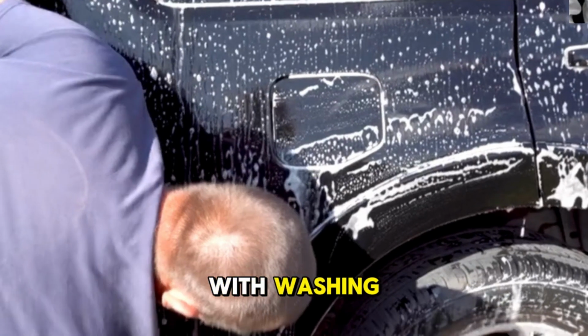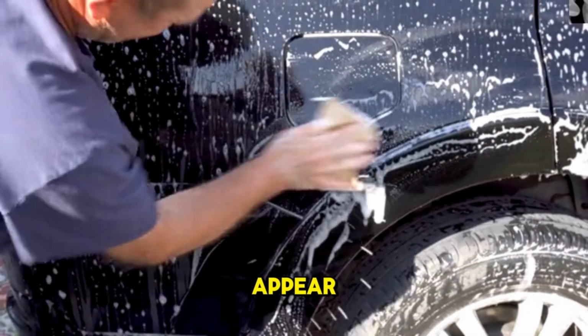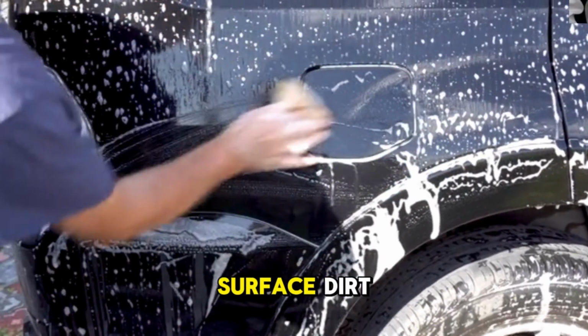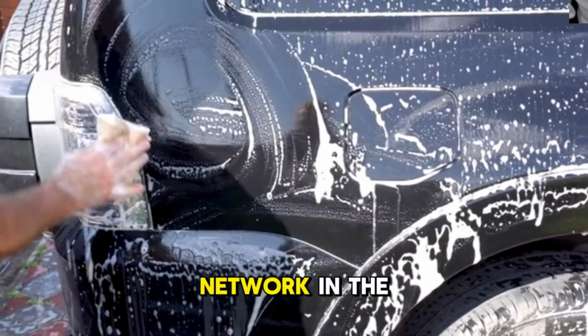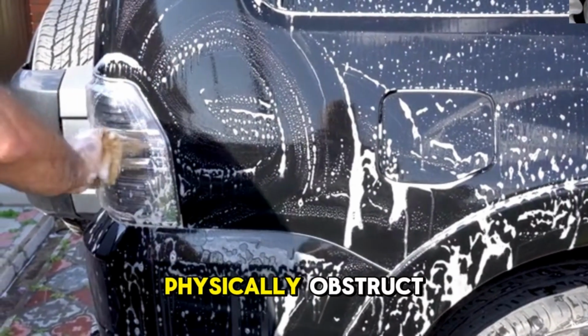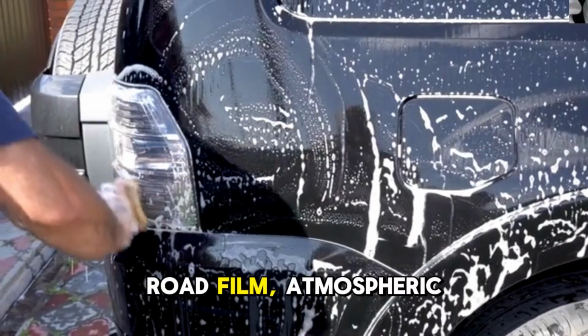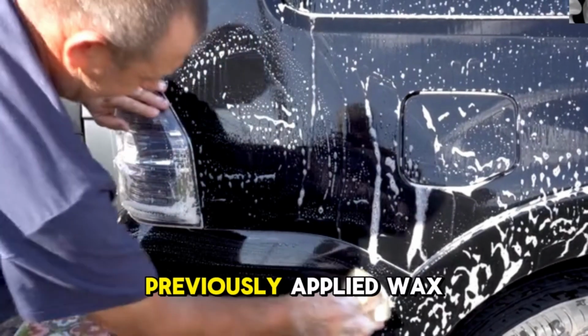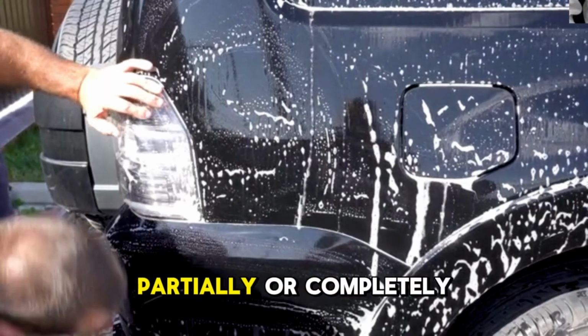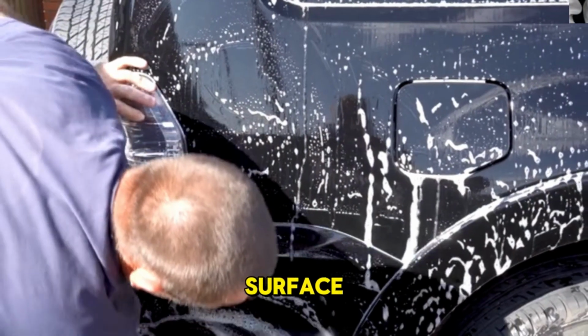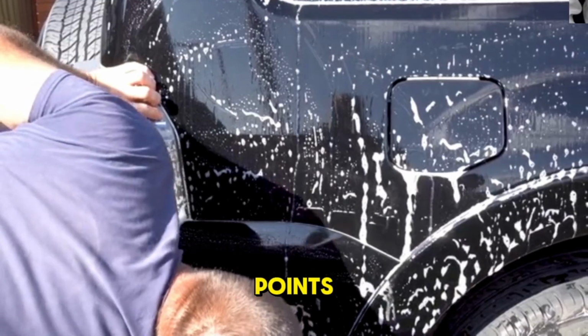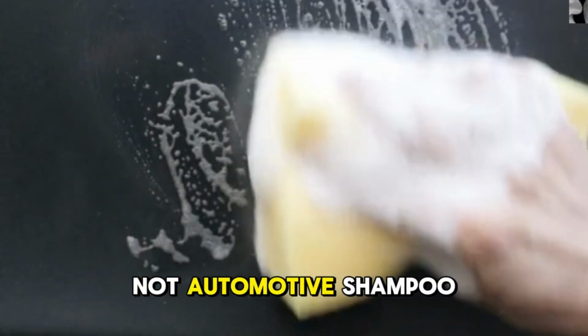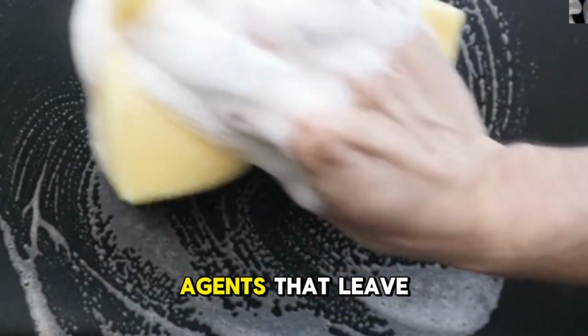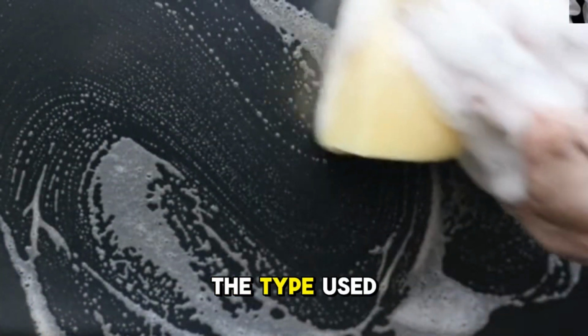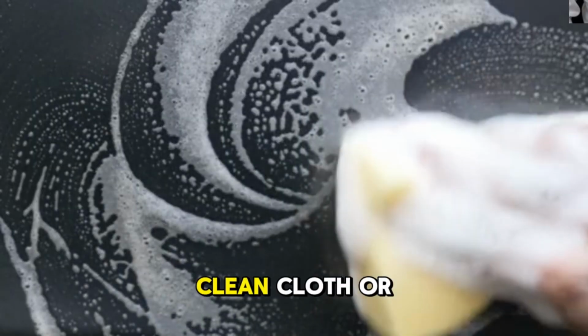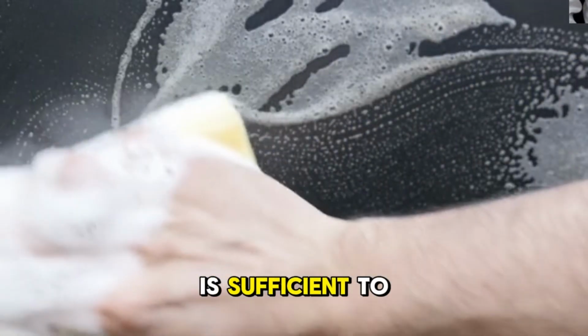The procedure begins with washing, and the washing stage is more important than it might appear. The purpose is not merely to remove visible surface dirt. It is to clear the openings of the fracture network in the clear coat from any contamination that would physically obstruct capillary penetration. Road film, atmospheric deposits, and the residue of previously applied wax or silicone products can partially or completely seal fracture openings at the surface, preventing the resin solution from finding its entry points. A thorough wash with standard dish soap, not automotive shampoo, which typically contains conditioning agents that leave a residue, but plain dish soap of the type used for hand-washing kitchen items, applied with a clean cloth or soft brush and rinsed completely, is sufficient to achieve this.